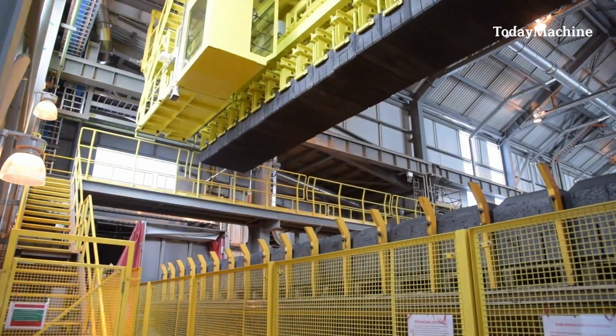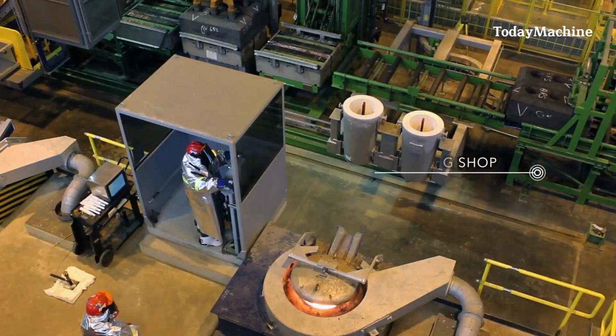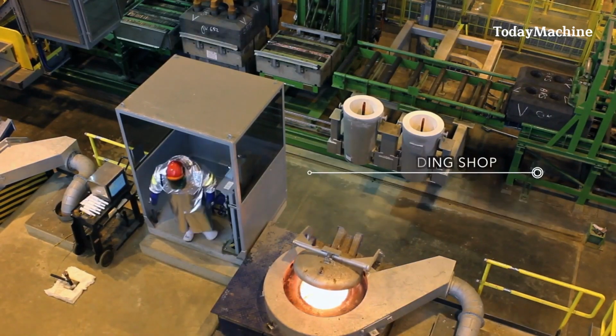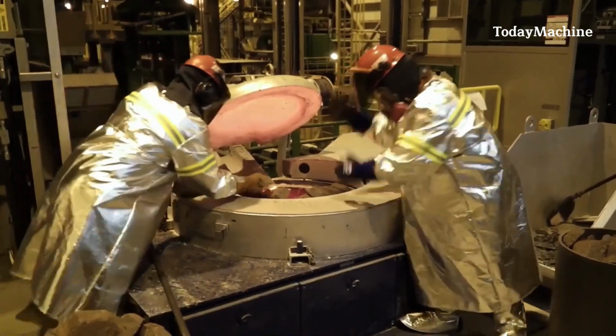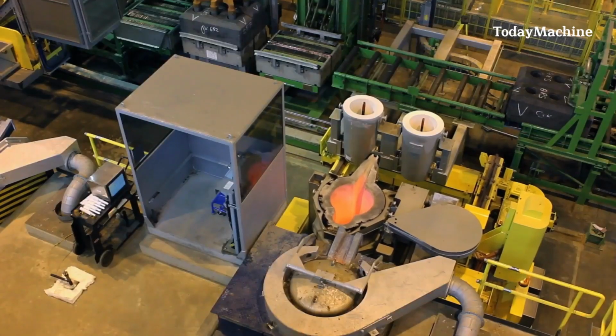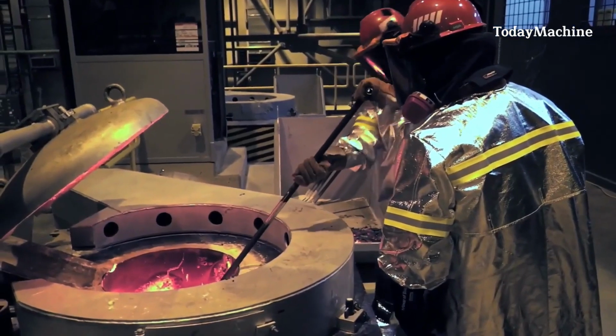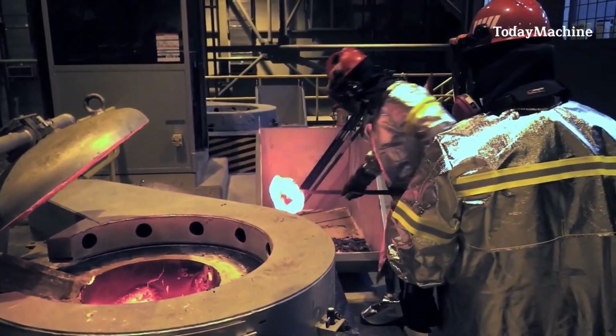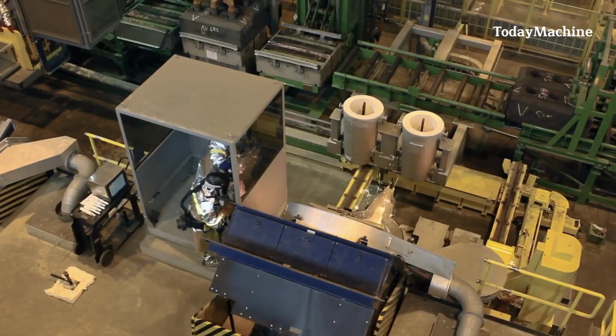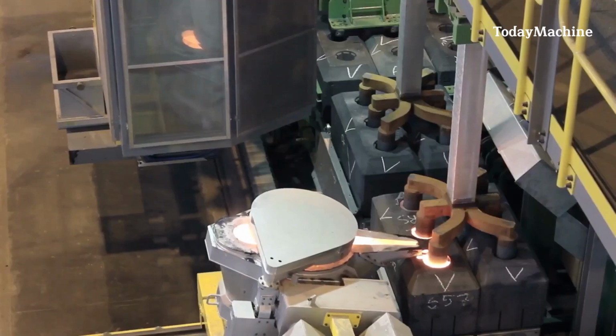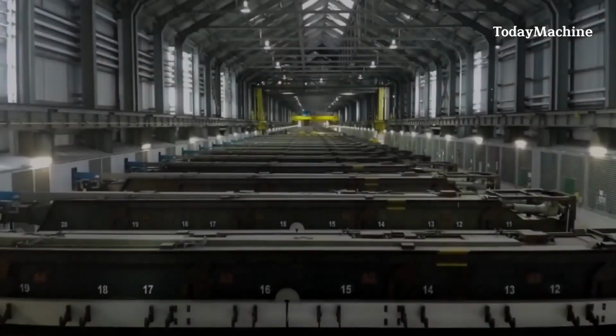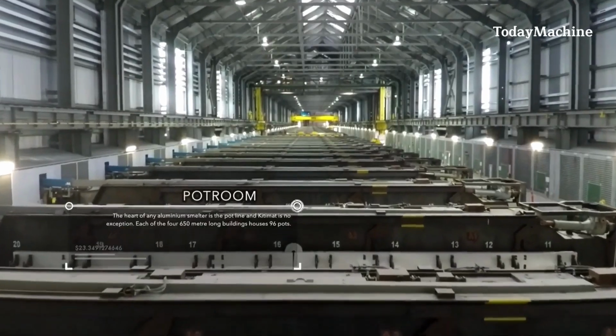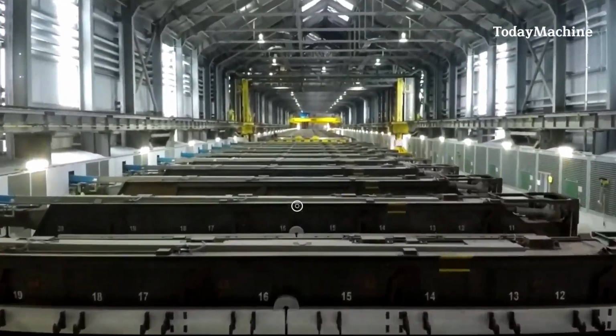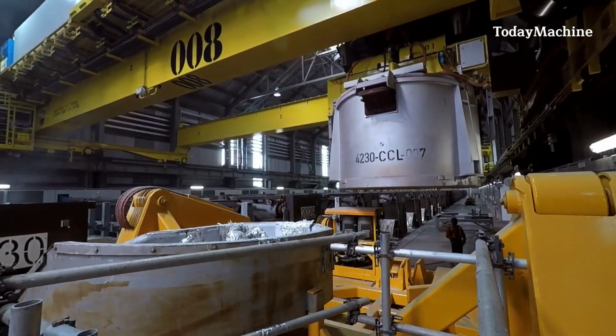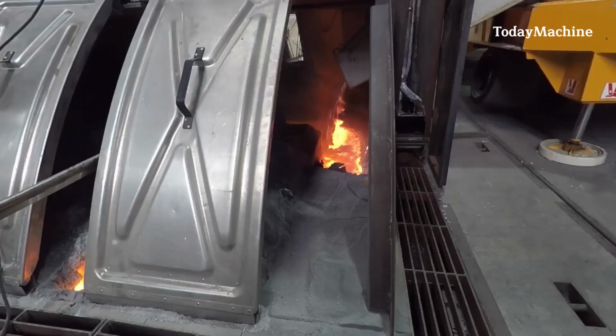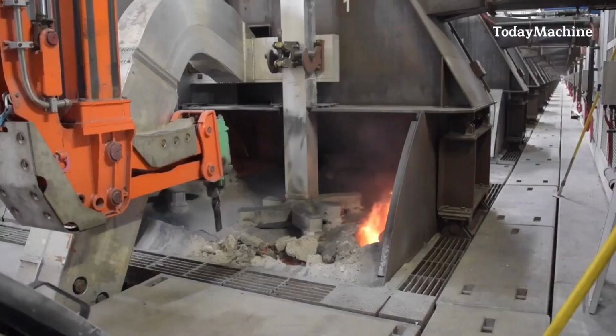Once the reduction process is underway, an electric current is passed through the anodes into the electrolytic bath, where the reduction reaction takes place. The electrical current causes a chemical reaction, separating the oxygen from the alumina in the electrolyte. The oxygen combines with the carbon anode, forming carbon dioxide, while the aluminum ions are reduced and sink to the bottom of the reduction cell as molten aluminum. The molten aluminum is periodically siphoned or tapped off from the bottom of the reduction cell and sent to the casting process. The smelting process continues continuously, with alumina continuously fed into the reduction cell, and spent anodes are regularly